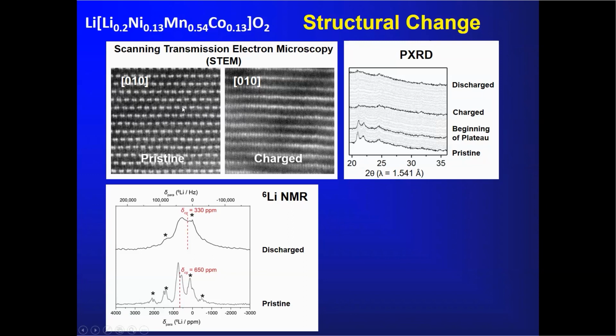If you contrast that with the charged material, you see that contrast of light and dark along a transition metal layer has gone. It's largely now washed out. And this is very much in accord with the transition metals disordering within the layers. You see there's not a lot of light between the layers where the light alkali metal ions would normally be. Of course, they're mostly removed in the charged state. But this shows us that we're not getting a lot of transition metal ions moving out of the layers, but they're disordering principally within the layers.